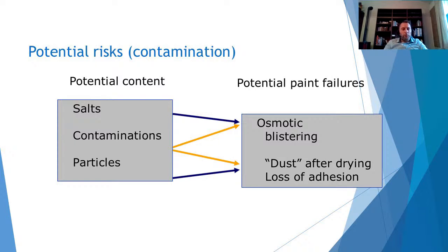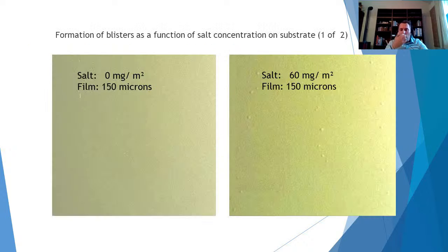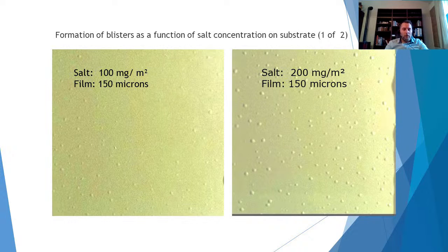Here we have some pictures that give us information regarding the quantity of salt and the effect on the coating. We have 4 pictures. These are the first 2. In the first picture, we have practically 0 milligrams per square meter of salt, and we don't have any trace of blisters. In the second picture, we have 60 milligrams, and you start to see some blisters. In the other 2 pictures the result is clear. When we have a big amount of salt, we have blisters, and blisters lead to corrosion and the consequent detachment of the coating.